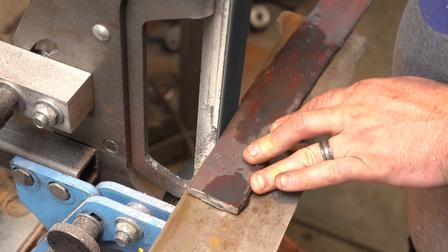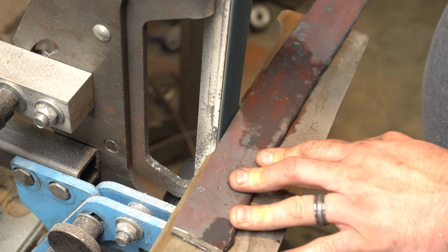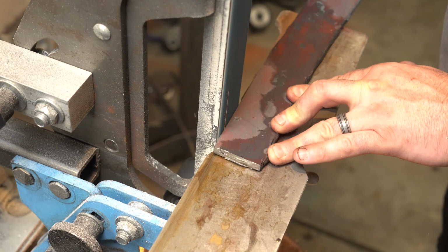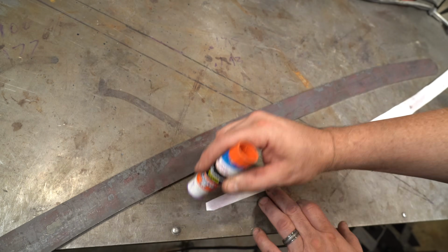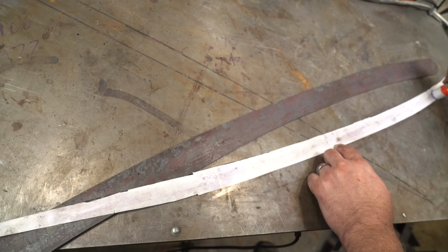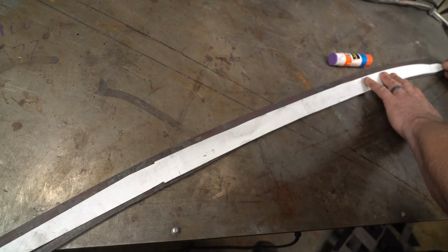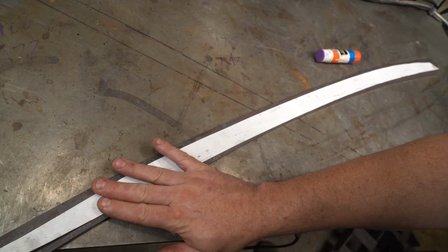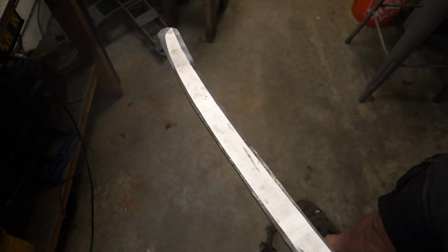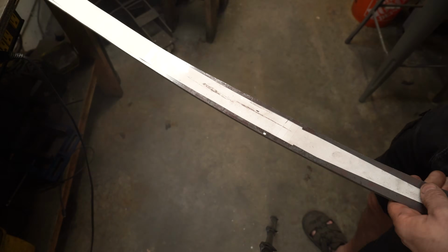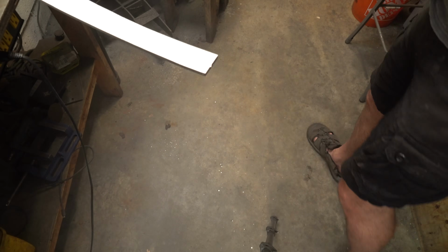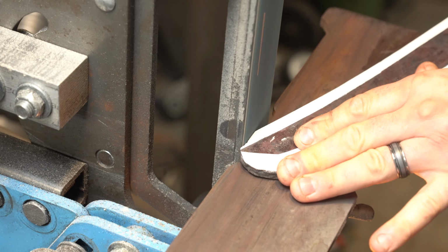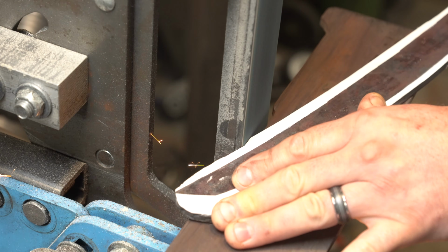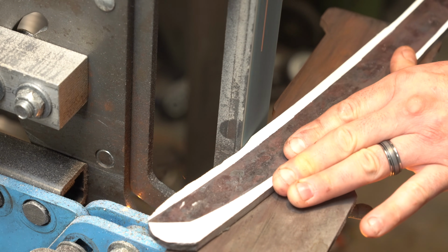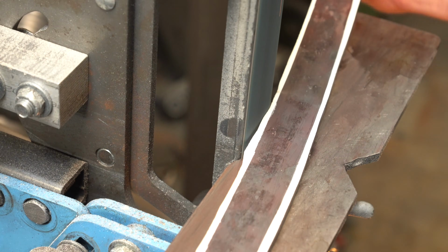And folks, before you run to the comments and tell me that the curve in a katana isn't forged in, I'm fully aware that the curve comes from a differential heat treat. But because this has Damascus cladding, I don't want to hamon over top of that. It will just conflict with the aesthetics. And for those of you that want to complain that it wasn't forged to shape, you can't forge these layered constructions with non-ferrous metals on the edge. They just delaminate. So instead, we cut them out.